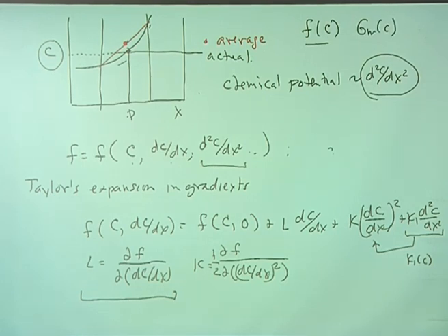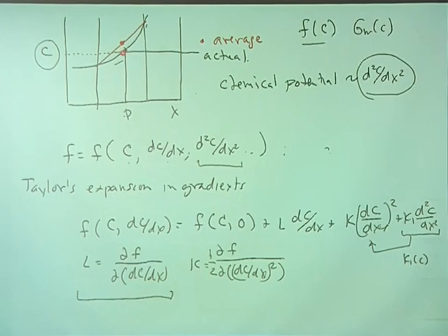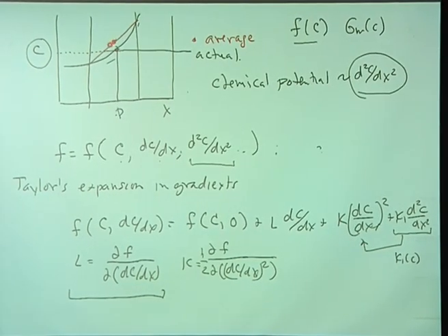What this says is that this is not the full story, because the composition of interest really isn't this one, but some sort of volume averaged composition that sits up here. The system senses the fact that in this interaction range, the average composition is not actually equal to the pointwise composition there. And so the fact that it's an average, and the fact that there's a difference, means that the curvature will affect the chemical potential.